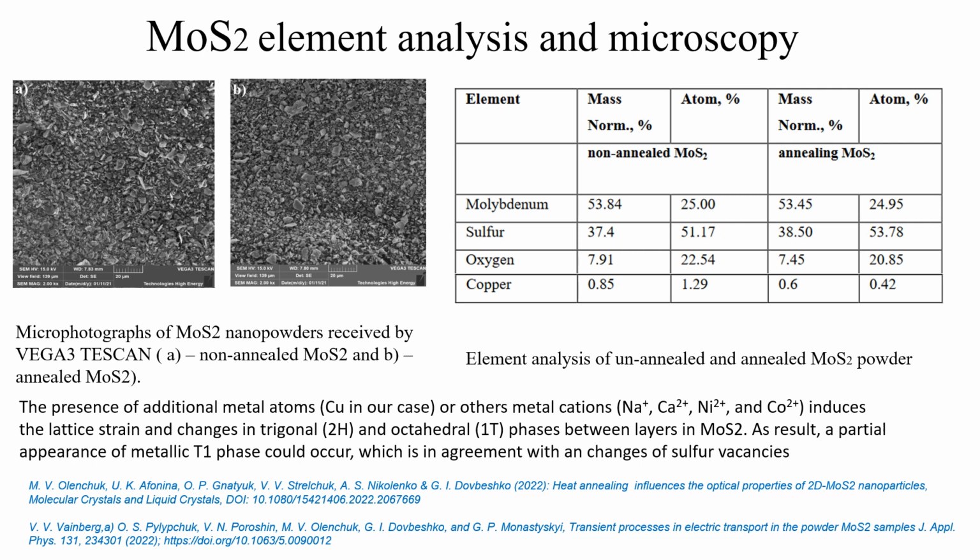Molybdenum disulfide consists of many particles deposited on a special electrically conductive substrate placed on the microscope stage. The molybdenum disulfide nanoparticles are annealed in a quartz tube furnace, purged and filled with argon gas, at a temperature of 700 Celsius for 1 hour. Images of the same sample in different places are presented before and after annealing.